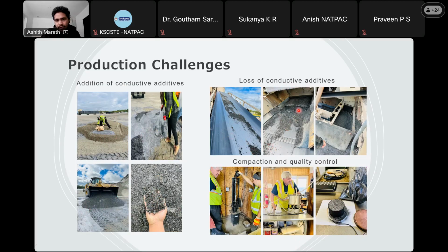we saw a lot of loss of conductive additives at the conveyor belt because of the presence of the graphite. The graphite had to stick to the surface of the conveyor belt, and it was sliding. The conductive finer portion of the mix was sliding downwards, and it was not carried upwards by the conveyor belt. So this resulted in a very high reduction in the electrical conductivity of the mixtures. These kinds of things we were not able to capture during our laboratory phase of study, and we had to compensate for the loss of conductive additives at the plant in order to achieve our target electrical conductivity of the mixtures.